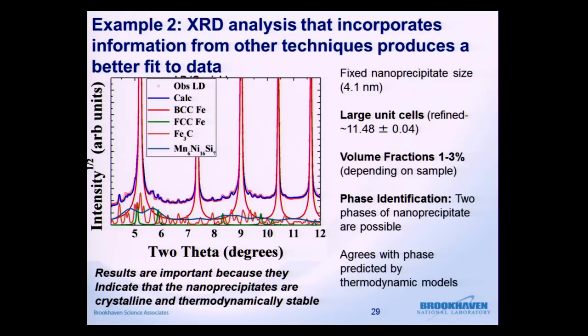So in the model, we fixed the size of the nanoprecipitates based on our SAXS results and the transmission electron microscopy. We refined the unit cell, so it returned a reasonable unit cell. It returned a reasonable volume fraction, and we were able to identify the phases of the nanoprecipitates. And this is an extremely significant result because the phase that we predict agrees with the thermodynamic models. So we were able to lend a great deal of support to the idea that the nanoprecipitates are crystalline. They're not just random clusters of atoms in the material, they're actually crystalline. And this means that they're thermodynamically stable and that they will persist over time in the reactor. So once you've created them, they will persist.